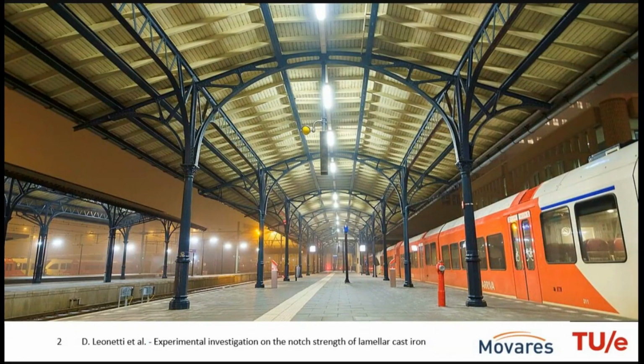So the context of this research is essentially related to railway canopies, which are these pretty long structures located in some railway stations in the Netherlands, and these are considered historical structures because they were built a couple of 100 years ago, and they are all made of lamellar cast iron. Now, generally cast iron, especially lamellar cast iron, is very strong under compression. It's comparable to high-strength steels, but under tension, it doesn't perform that well, as we will see.